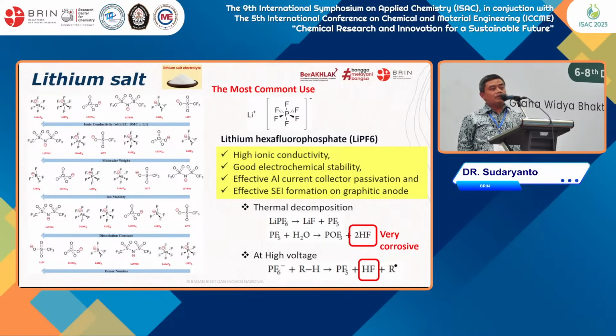But this electrolyte is very challenging if we use it for high voltage lithium ion battery, because this electrolyte, when used in high voltage, easily degrades, resulting in HF, hydrofluoric acid. This is a very strong acid, meaning very corrosive, and especially when it meets water, sometimes it can react with water and also with the solvent itself to form HF. So if there is high acid in the battery cell, of course the cathode will have a big problem.